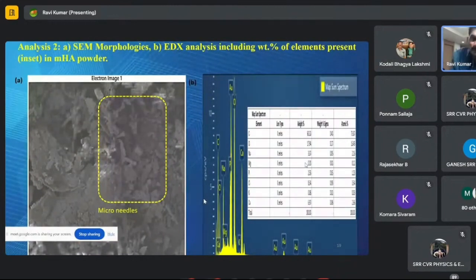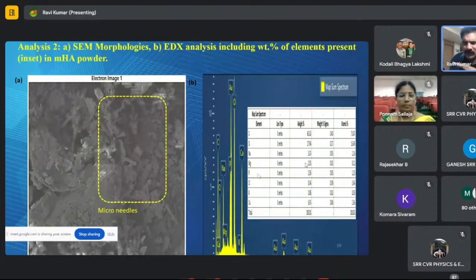Also, we tested the surface morphologies of MHA and did EDX analysis, that is elemental analysis. We tested what kinds of elements are present in this material, at a particular area with micro needles. You can observe these needles here. There are several elements, but calcium and phosphorus are showing here. These are the two important components obtained from the MHA. You can see the signal of phosphorus, and carbon and other elements coming from the jute fiber. There are also some minor elements found here: magnesium, calcium, potassium and oxygen, and you can also find sodium along with the original elements.